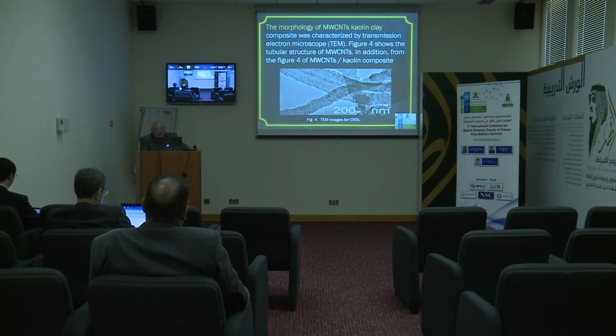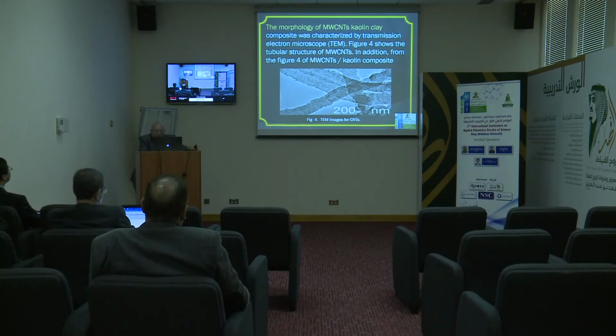The morphology of the multi-wall carbon nanotubes kaolin clay composite was characterized by transmission electron microscope. The figure shows the tubular structure of multi-wall carbon nanotubes. In addition, the figure shows the kaolin composite. These are the images for carbon nanotubes.